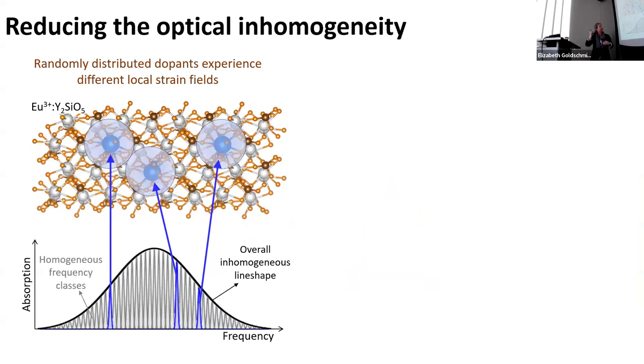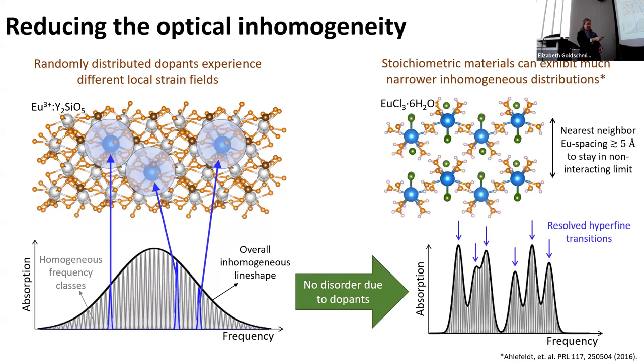Okay, so reducing the optical inhomogeneity, this difference that each atom has in its optical energy, is due to slightly different electric fields at each atom, which is hypothesized to be dominated by point defects in the lattice. What's the biggest point defect in a rare earth doped crystal? Well, it's the rare earth doping, right? In a traditional rare earth doped crystal, you have randomly placed rare earth atoms substituting for something, and the microscopic arrangement of them is different for each one. Each one sees a different microscopic arrangement of all the others, and that changes the field slightly, and then I get this inhomogeneous broadening in the system.